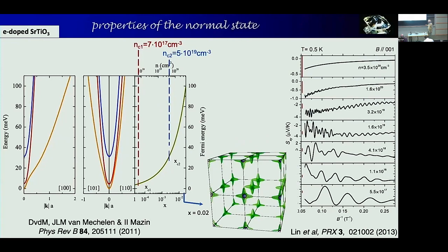So you start by filling this first band. At some point you go through, let's say, a Lifshitz transition, where you start to occupy a second band at a critical doping. That's calculated over here, 7 times 10 to the 17 per centimeter cube. And then at a second critical doping over here, you start to occupy the third band. Most of the game that we are talking about is in doping ranges where you go maybe as far as this and down to almost zero doping. That's what we were talking about.